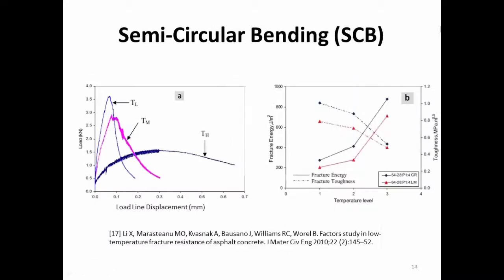Okay. So here are some typical representative loading curves for the SCB test. These 3 curves are for the same kind of asphalt specimens, but at different temperatures: low temperature, middle temperature, and high temperature. One thing we can notice is that as the temperature changes from high to low, the peak load increases. What does this mean?